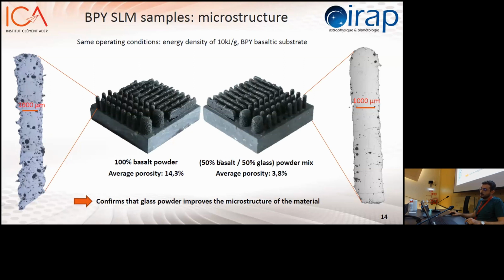Just by changing one condition, the proportion of amorphous powder, we have made a mix between 50% basaltic powder and 50% glass, because we want some reasonable content of glass and not 100% glass, which would be weird on the Moon. You can see that the microstructure is generally much better and more regular, with a lot fewer porosities, because we are dropping to 4% porosity. That confirms that just adding some glass material in the analog actually improves the microstructure a lot at the end. Probably we don't have the exact reason yet, but probably it is because of the mobility it brings, as I was saying, and all the physical properties, like optical properties, are actually changing.